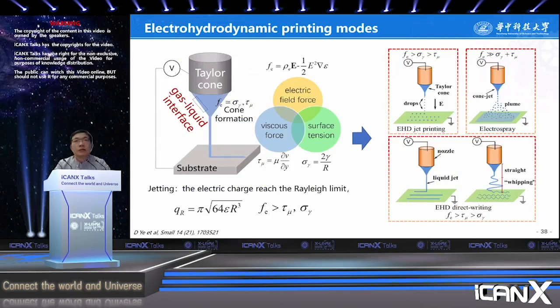There are three kinds of force in the jetting process, including the electric field force, the surface tension, and the viscous force. Based on the relationship between these forces, one can get three printing modes, such as EHD jet printing that works in a drop-on-demand manner, EHD direct writing that works in a continuous manner, and electrospray that deposits film directly. EHD jet printing is usually adopted to fabricate micro and nanostructure arrays.